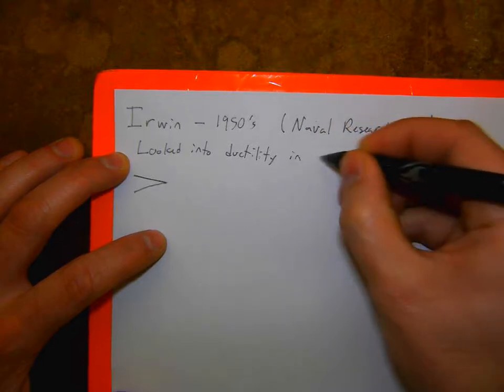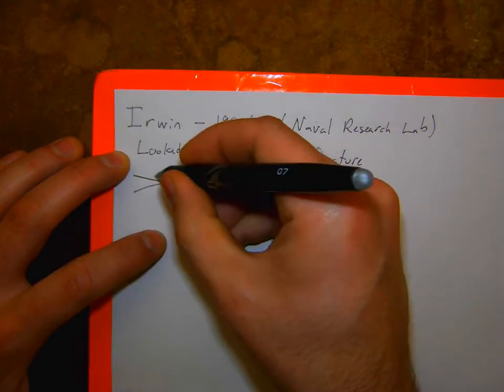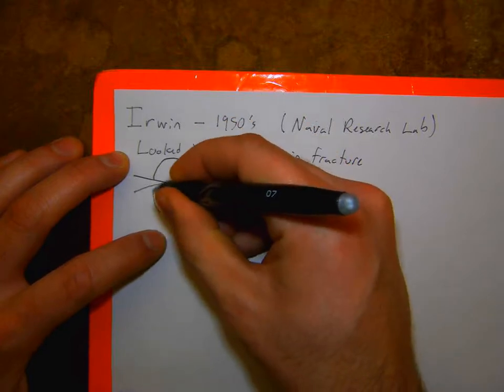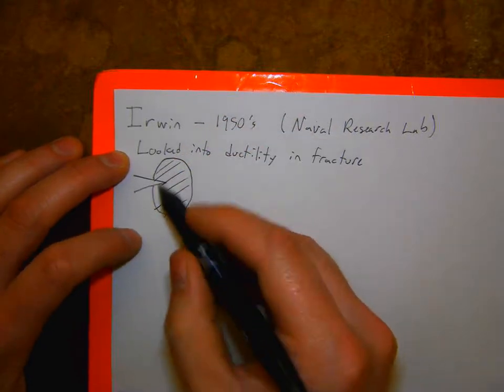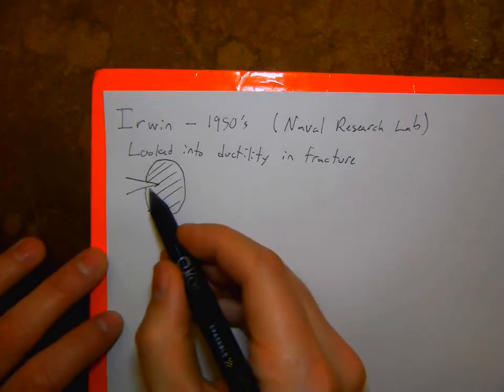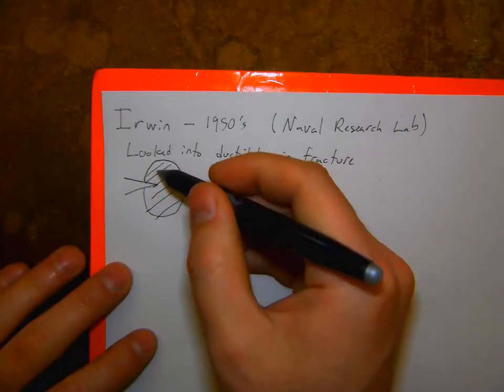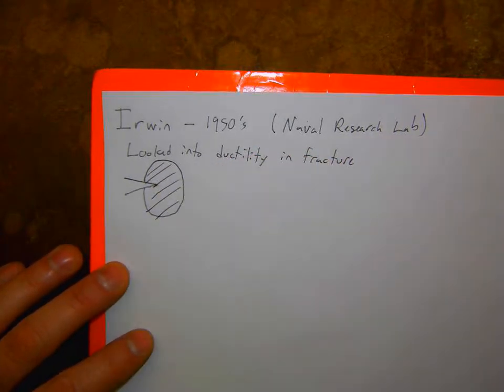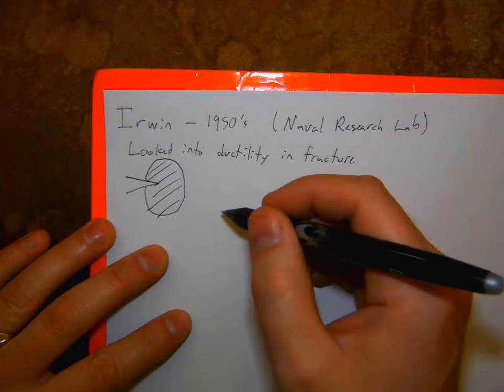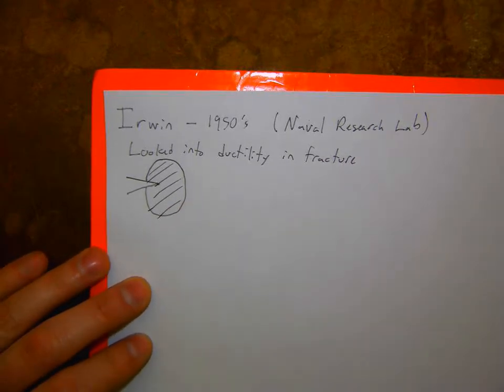And he found that around the tip of the crack, there was some region where there was plastic deformation. So you didn't necessarily see, like in that silicon wafer, a catastrophic brittle crack propagate immediately. Even around a very sharp crack, you see some amount of deformation, some amount of plasticity near the tip of that, and then eventually fracture starts to happen. So this is more like that hydrogel that we saw, where the crack can deform and open up a lot before it actually propagates through the material. And so this plastic zone size then depends on whether we're in a state of plane stress or plane strain, which I'll talk about in a little bit.